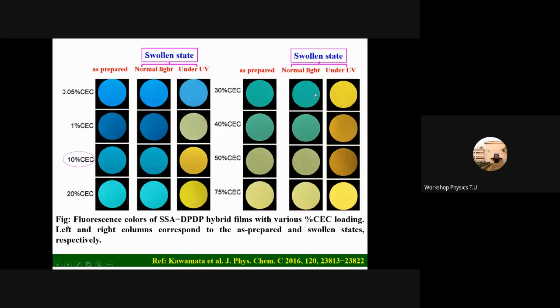You can see the second column. But the interesting thing is that after putting the solvent, when we expose the film under UV light, we see the colors. In the last column, you can see the colors. And from this experiment, we selected this 10% CEC.